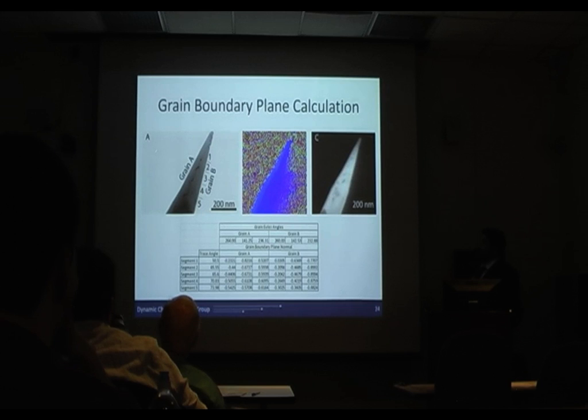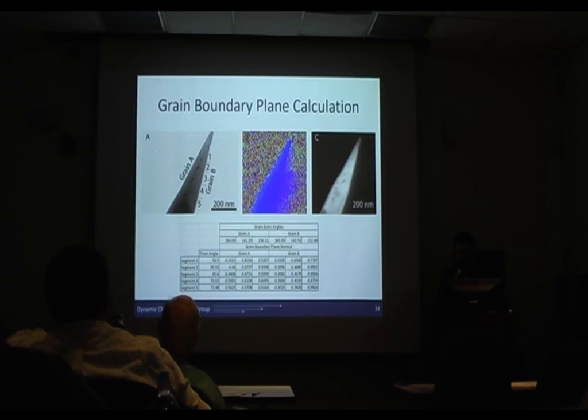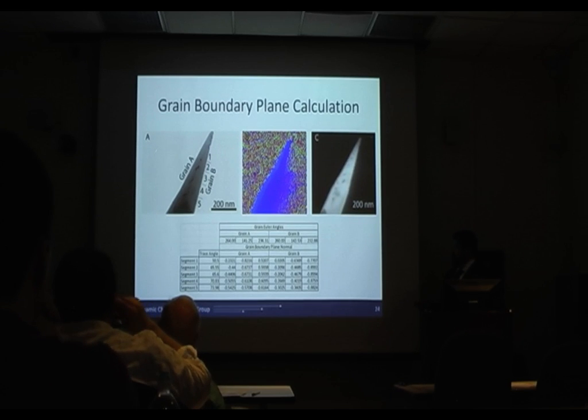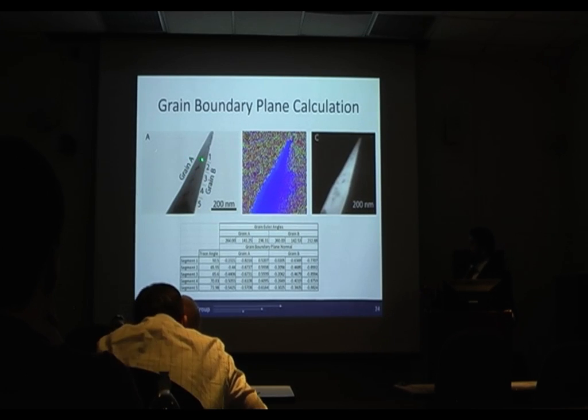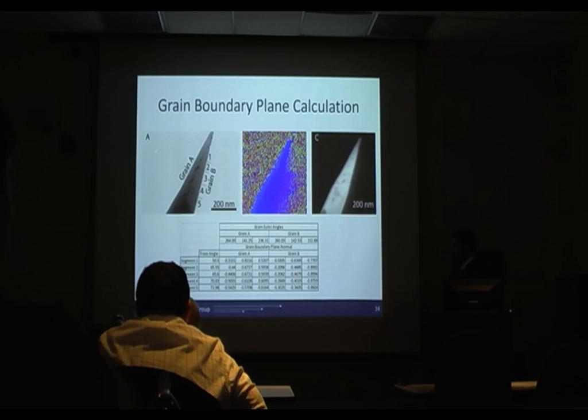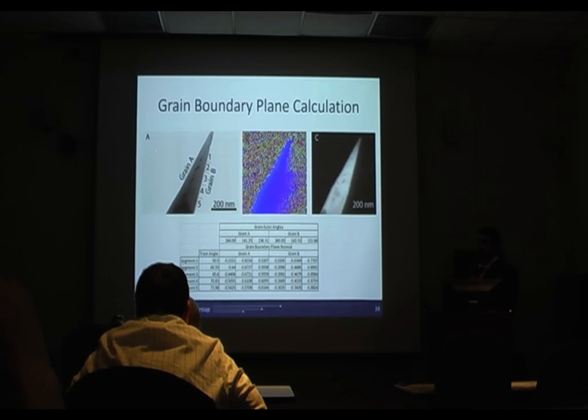So moving on, we wanted to see how we could apply this to other materials as well, especially atom probe specimens. What's shown is a 5456 specimen, and on the left we can see the grain boundary has been decorated by these precipitates, and by getting an ACOM scan, we can then calculate the local grain boundary planes for each of the grain boundary segments between those precipitates.